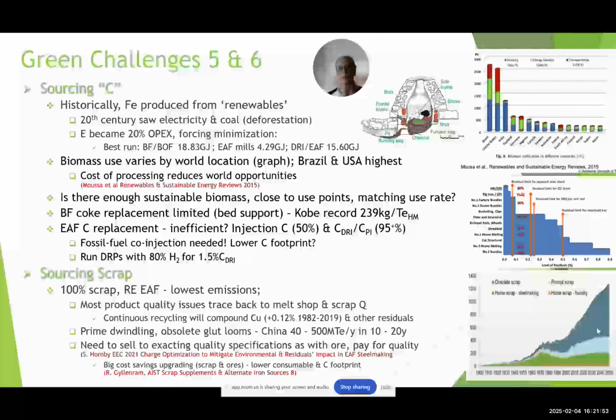Blast furnace coke replacement is limited because it supports the bed. Kobe Steel has made a phenomenal breakthrough and has the lowest coke in the world at 239 kilograms per ton of hot metal. Arc furnace carbon replacement could be inefficient. Injection carbon currently is only 50% efficient, whilst the carbon contained in situ in DRI and pig iron is 95% efficient. Fossil fuel has been required as co-injection with the biomass, which may not lower the carbon footprint very much. My suggestion would be to run the direct reduced plants at 80% hydrogen and maintain the in situ carbon in the DRI. Sourcing scrap, 100% scrap is the lowest emission steelmaking process.